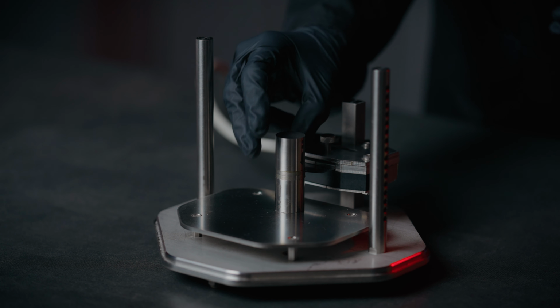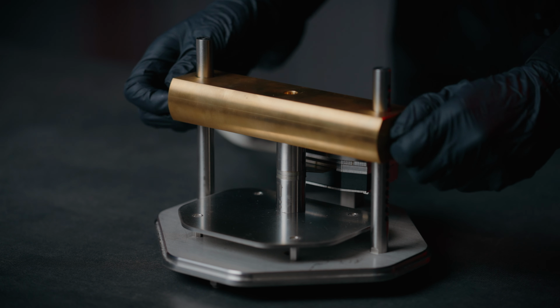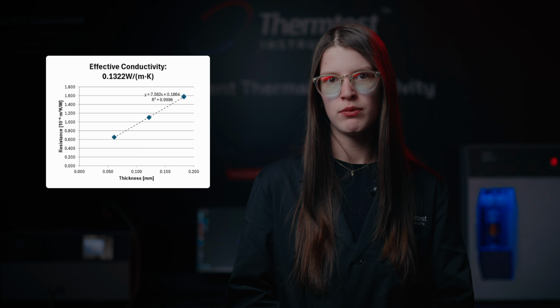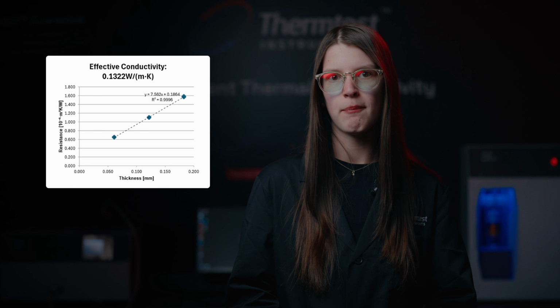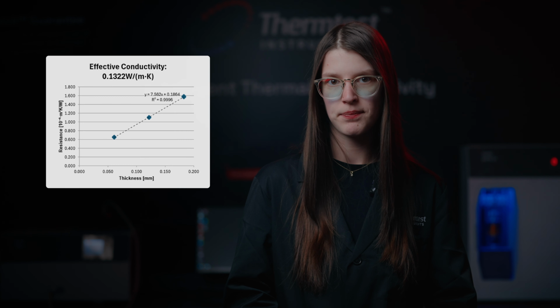Tape layers were stacked to increase thickness, and thermal resistance was measured versus thickness, a method aligned with ASTM D5470 and E1530. Testing was done at room temperature using a 9.9 mm radius TPS sensor. And because the samples were naturally adhesive, no contact agent was needed.